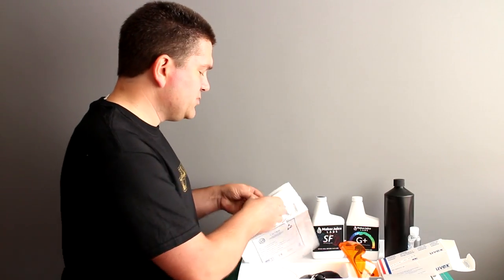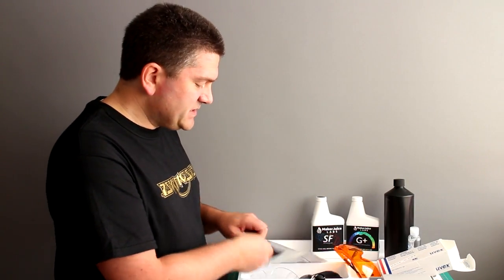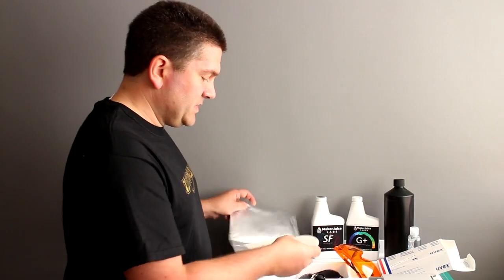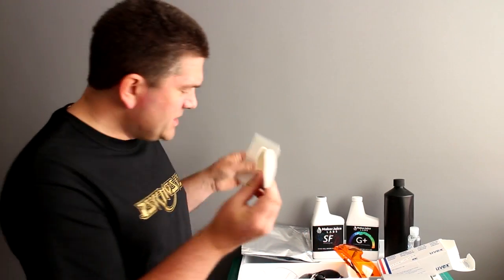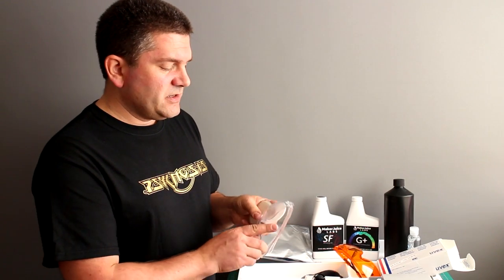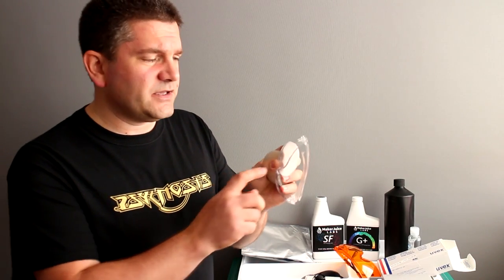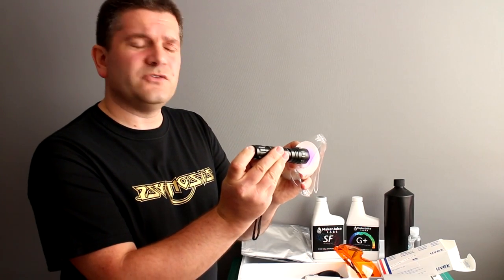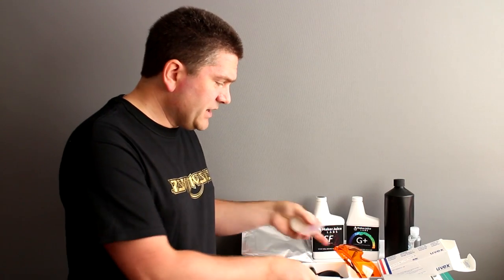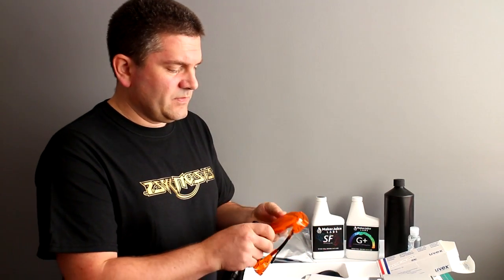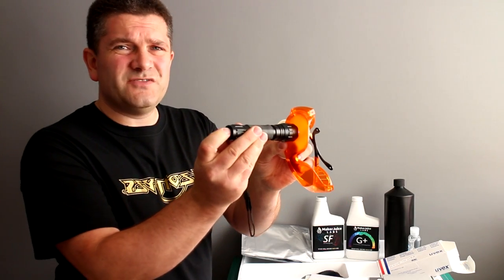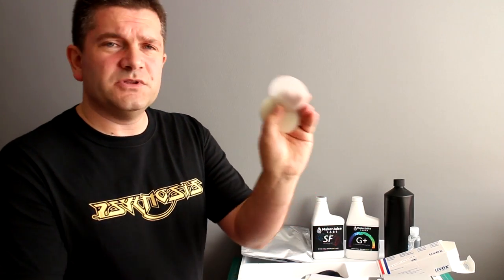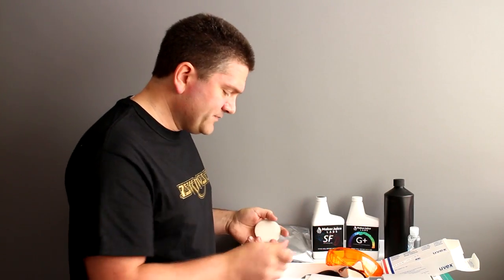What you can do with that is print out some test pieces like so and you can use these in your various experiments to see how much UV light you can pass through different surfaces. I'll show you an example of a normal polycarbonate goggle that has got no UV protection at all. As soon as you shine light through that it goes through and you can see. But if we use our goggles you can shine as much UV light as we like into that and that's never going to show up on the other side because it blocks almost all of the UV light going through.